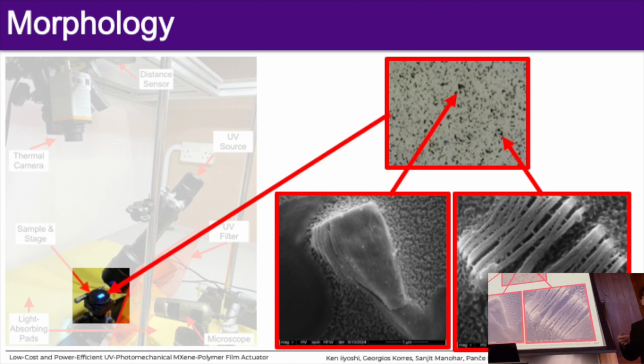So answering the question, how does this film look on a more zoomed-in scale? For example, if you zoom in with a microscope, the mixture of MXene embedded in the polymer can be clearly seen. It's quite a homogeneous, uniform mixture. And on the SEM, if you zoom in to a 1 micrometer scale, you can clearly see the structure of the titanium carbide MXene. Basically, it's an accordion-like structure embedded in a sea of cured polymers. These sandy-looking grains are the polymers.